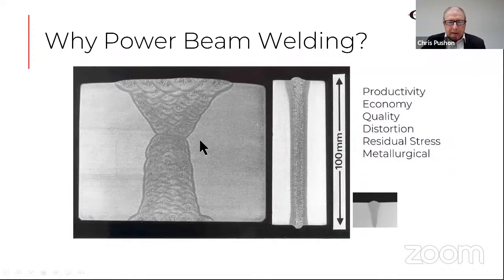So in contrast, the electron beam process produces a weld in a single pass. So this is 100 millimeter thick low alloy steel. It produces a single pass weld, which is actually parallel sided. And this gives you some benefit also in terms of distortion, shrinkage, and residual stresses. Whereas this does give some out of plane bending stresses, which cause deformation.